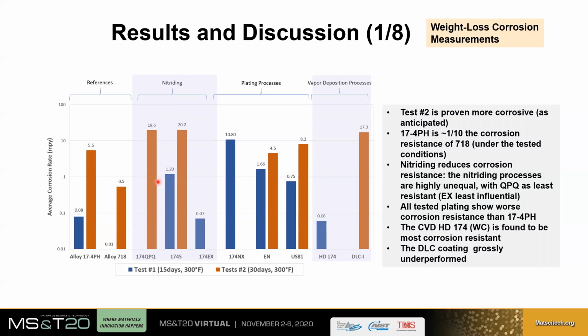So obviously, by seeing much longer bars here, we do have much more corrosion when there is nitriding. If we look at 17-4 PH, for which we have most of the results, we can see the corrosion is increased significantly, whether with QPQ or with higher nitriding. We do happen to see a little bit less corrosion when we use this other supplier, which uses a low temperature nitriding process. But keep in mind also the amount of nitriding is very, very limited. And this is essentially why we are seeing less corrosion here than you would see with the other processes. So essentially, nitriding does not improve corrosion.